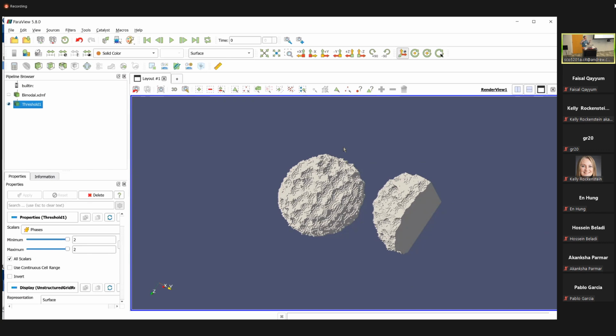And the reason that's important is because that's what Dream3D wants to start from to then put these transformed twins or laths into the structure. Right now we just make nice equiaxed structures as the original parent phases, then we put these twins in, and it never quite looks like the structure that we looked at yesterday in the Midas data set, where you get these massive grains that are heavily twinned in a whole variety of complicated ways. We just have never figured out a way to recreate that with this sort of shape type insertion.